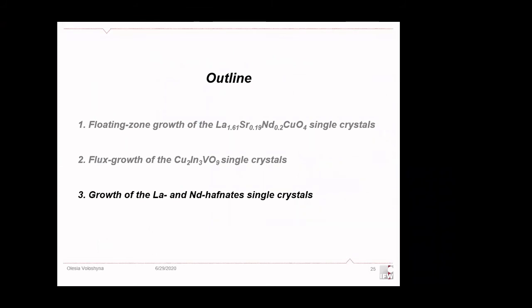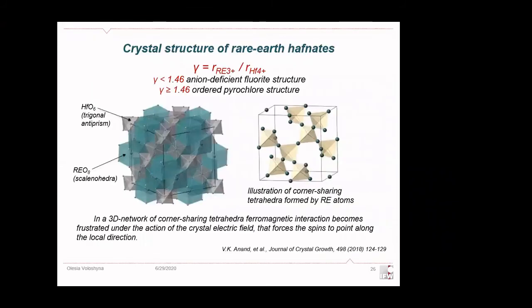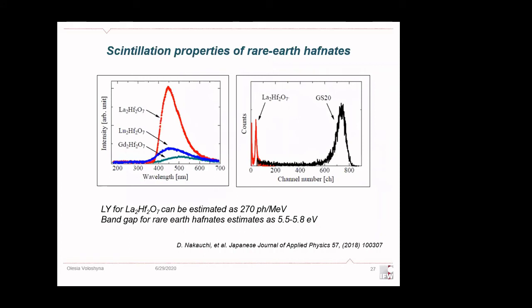So now let's move to the final part about lanthanum and neodymium hafnates. The structure of these compounds strongly depends on the ratio between the rare earth ion and the hafnium ion, and we are strongly interested in hafnates with a pyrochlore structure, where the rare earth atoms sit in a 3D network of corner sharing tetrahedra. And for such materials, the scintillation properties were also studied, and as you can see, the properties are not so good. The light yield